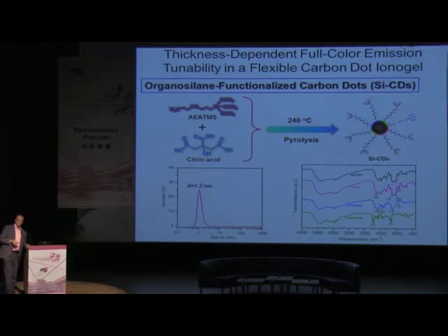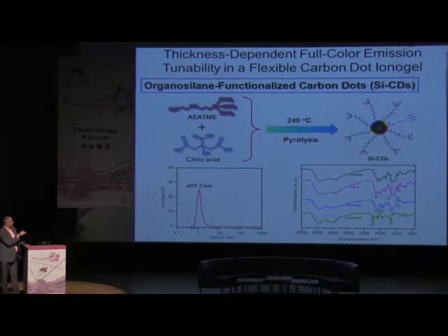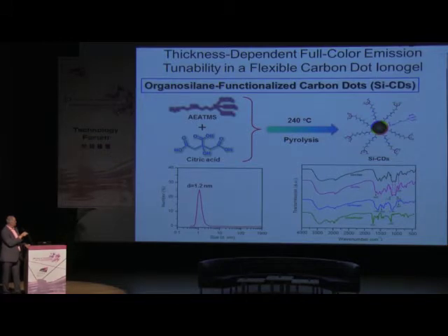For us, it was very easy to transfer our expertise from quantum dots to carbon dots, because for us these are all colloidal nanocrystals, colloidal nanoparticles. They have a light-emitting core, as I mentioned, and they have some surface chemistry. Surface chemistry is important here if we want to make composite materials out of them. So for making ionogels, we started from organosilane functionalized carbon dots, short name like here. For that, we use a very environmentally friendly synthesis. Citric acid is a cheap organic molecule, and by high temperature pyrolysis in the presence of this silica-containing molecule, we get particles which are schematically shown here.